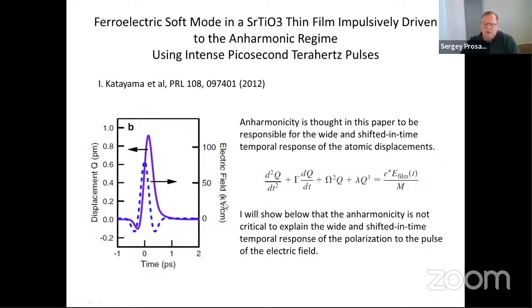This depends on what we want to have. For example, in this plot, you see the response in strontium titanate at low temperatures. The response is wider, and it can have oscillations after the signal. If we want these features, this can be done on, I think, any material, actually. But closer to phase transitions, we have a larger susceptibility of the system, and correspondingly, this response will be wider, at least. But what I told about was a little bit different.